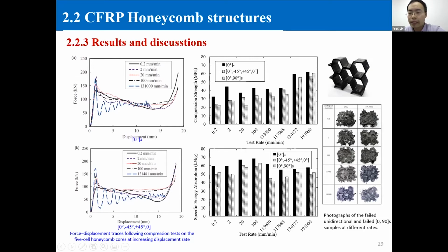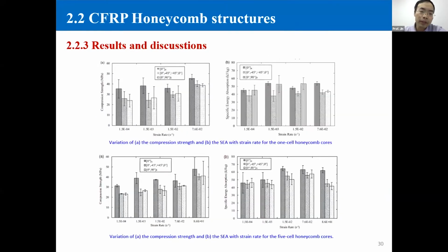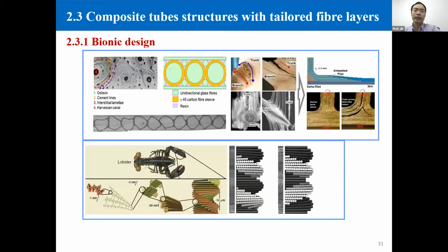And the figure on the right-hand side shows the failure mode of those crushed samples at different loading rates. And this is the final result, showing both compression strength and energy absorption of those two structures at different loading rates.